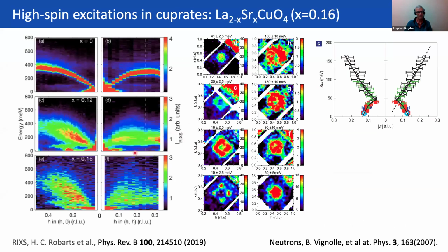So here's some rare data just to show that. With RIXS, we can see these broad things. And then as you come down in energy, we see scattering near pi or half. These maps here, the center of these maps is a half. So this is at 150 millivolts, and we drop down to say about 50 millivolts,